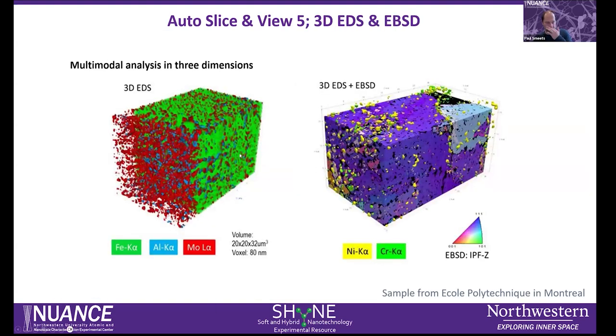This is just an example of multimodal acquisition, where you have 3D EDS data and 3D EBSD data. This is not work performed here, but just to give you an idea—these are precipitates in an alloy. You can elucidate the chemical composition of the alloy, but also get crystallographic information with EBSD, for example looking at where grain boundaries near these precipitates are. So this multimodal acquisition is possible.